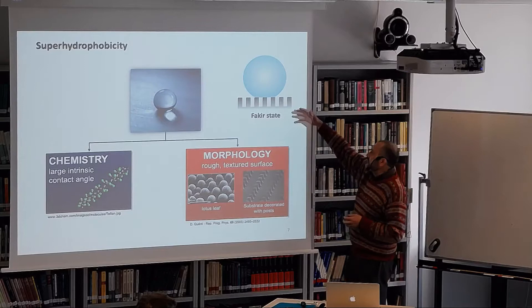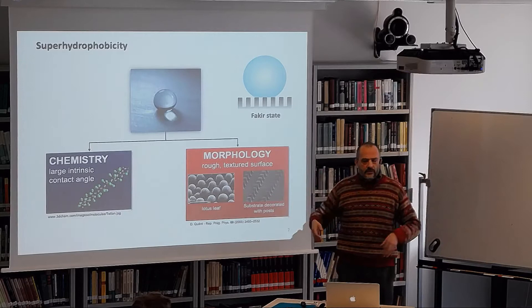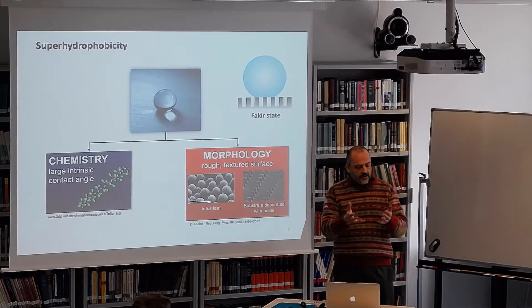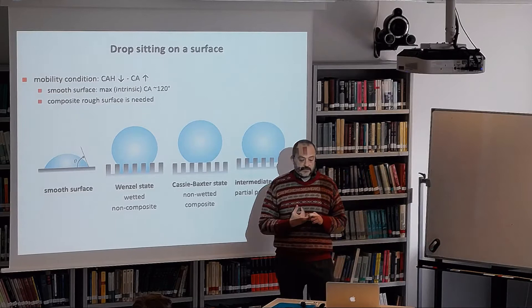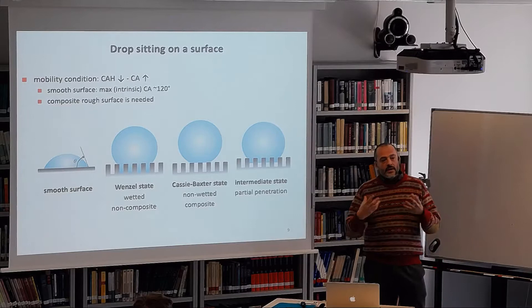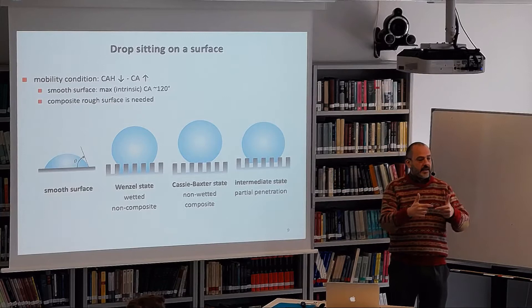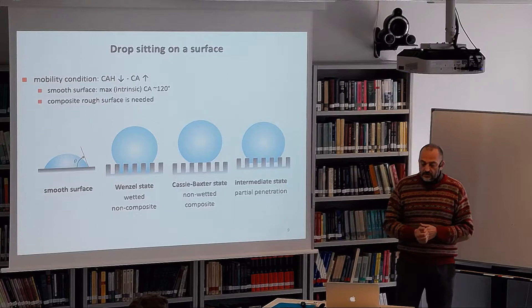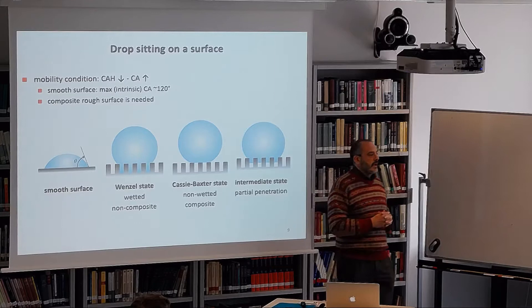On a super-hydrophobic surface, the droplet is in a kind of fakir state — staying on pillars, or on a random morphology. The key is a very high contact angle but also a very low contact angle hysteresis. When placing a droplet on a surface, there are two contact angles: the receding and the advancing. For example, if you inflate the droplet you get a different angle versus when you deflate it. The two contact angles are different.